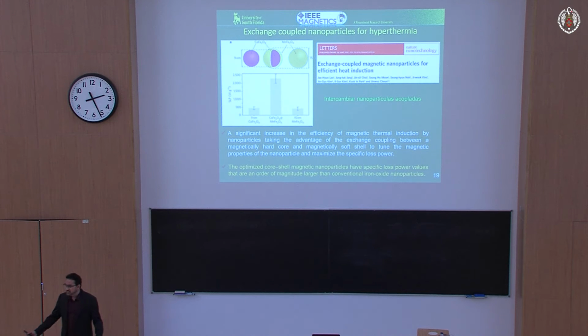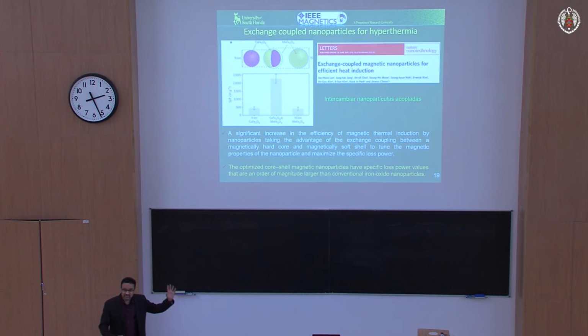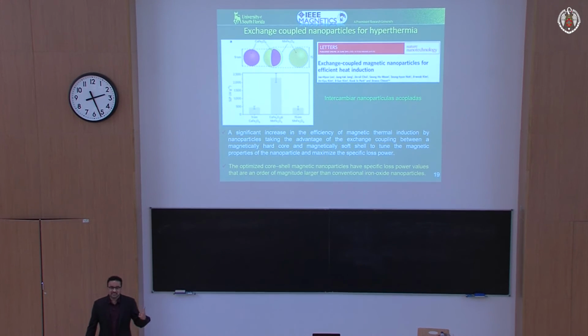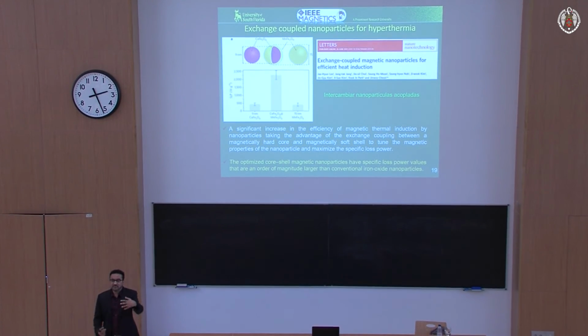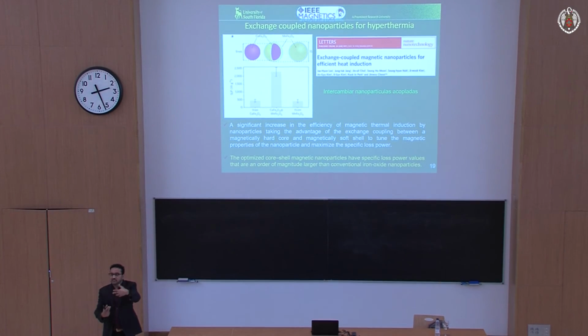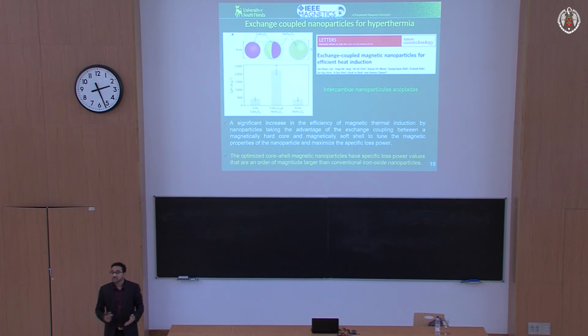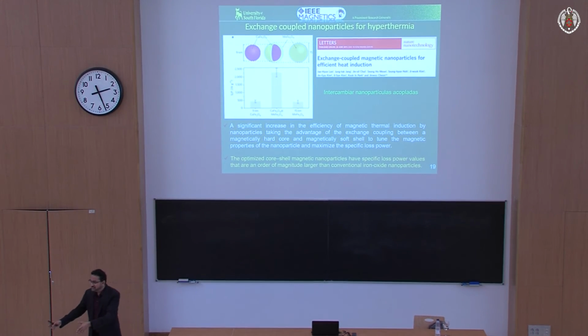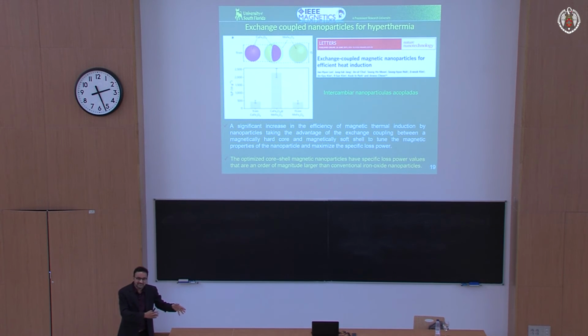This is all oxide, there is no Kirkendall effect, they're very stable. And they actually had a large exchange bias. So these are nano spin valves. Each one of them is a spin valve by itself. It's showing exchange bias. And they reported exchange bias. They also reported a very large SAR value. So basically, this is an extremely good way of having exchange coupled systems which can give you a large SAR value. This is what I meant by what is good for spintronics is also good for nanomedicine here.